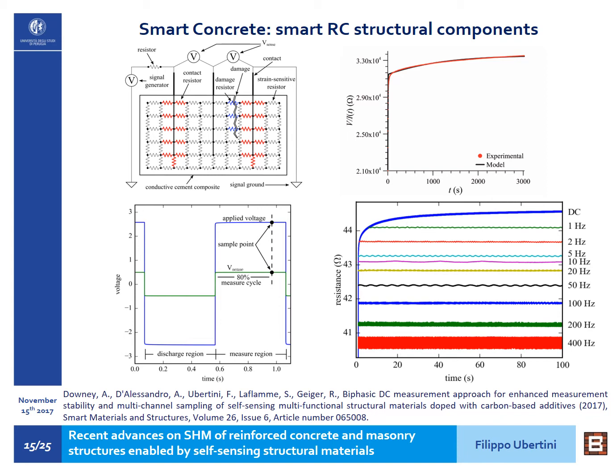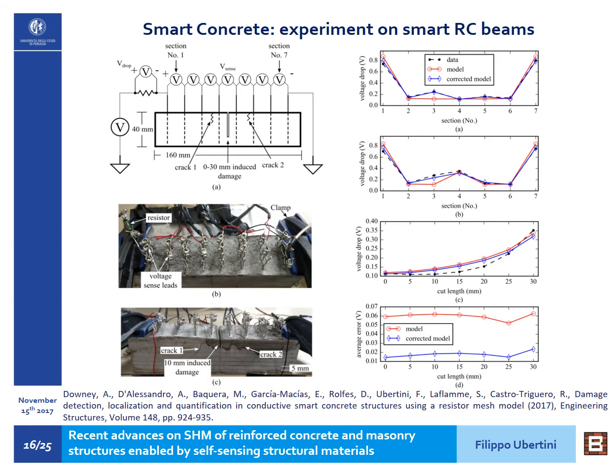As we see in the diagram on the bottom right, in this way, we can eliminate the time drift that we see in the resistance versus time plot in the case of direct current configuration, but which we don't see in the case of 1 Hz, 2 Hz, and 5 Hz, and so on, square waves. So, since we are able to achieve steady voltage drops across an element made of smart concrete, we are also able to detect changes in these voltage drops, for instance, following the formation of a damage.